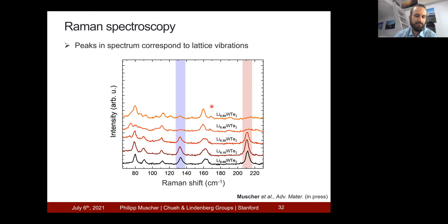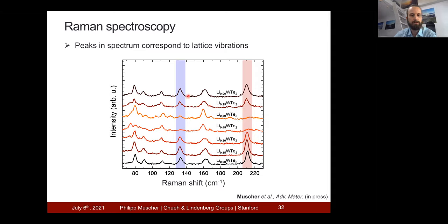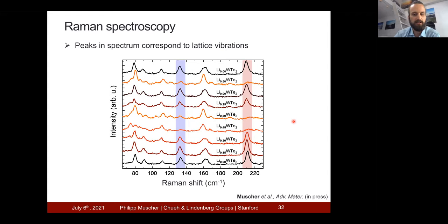After lithiation, we can use our electrochemical platform to remove the lithium again, and we can see that as we remove the lithium, these peaks reappear. We can do the same thing for a second cycle of lithiation and delithiation, and we can see that we have full reversibility of the Raman spectrum with lithiation. So you can see that lithium insertion can tune the vibrational spectrum reversibly, which has implications for the thermal properties of this material.